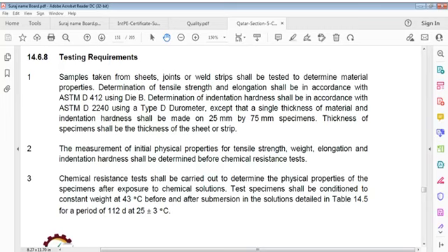Testing requirement: samples taken from sheets, joints, or weld strips shall be tested to determine material properties. Determination of tensile strength and elongation shall be done in accordance with ASTM D412 using die B. Determination of indentation hardness shall be in accordance with ASTM D2240 using Type D Durometer.